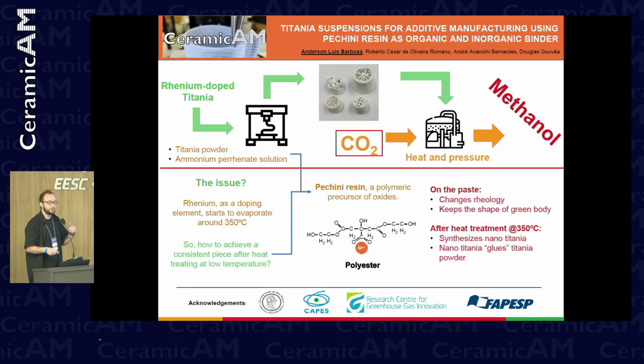The polymeric resin will start to burn and turn into the titanium oxide in this case, forming nanotitania. This nanotitania will work as a binder, gluing the titania powder that's already in the suspension. So we could get solid pieces, as you can see here, sintering at 350 degrees. That's it. Thank you.